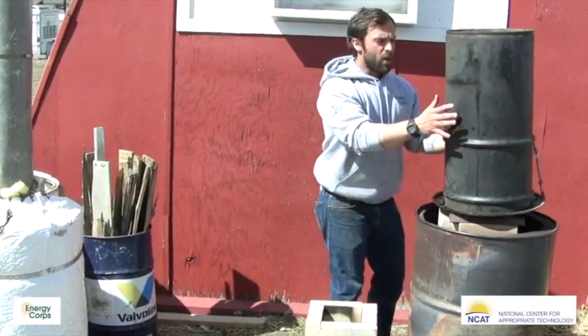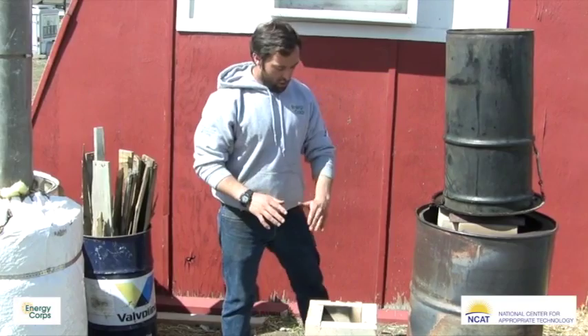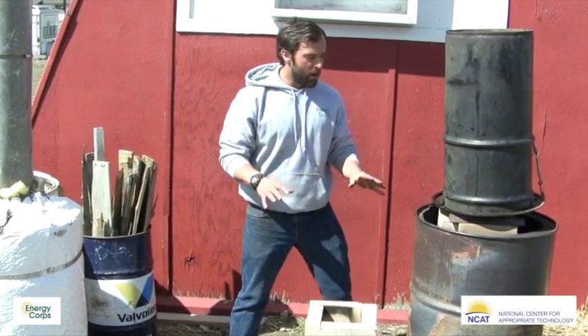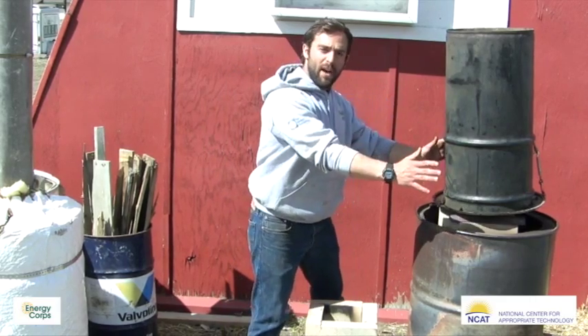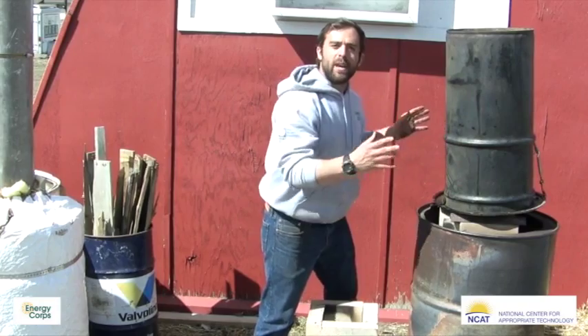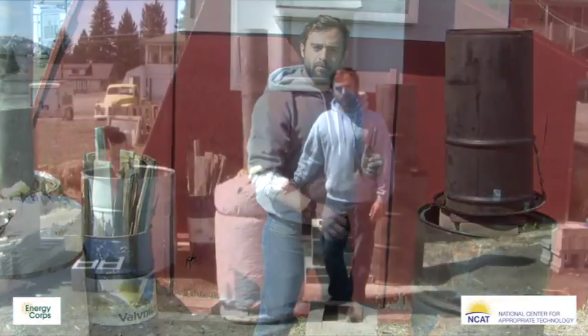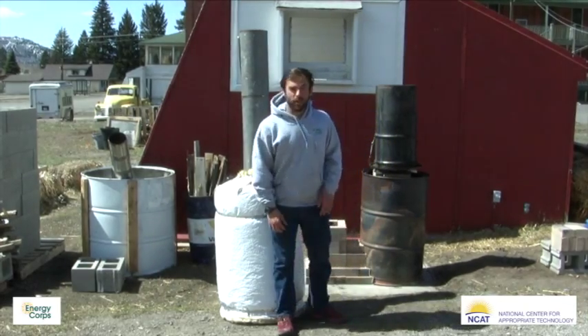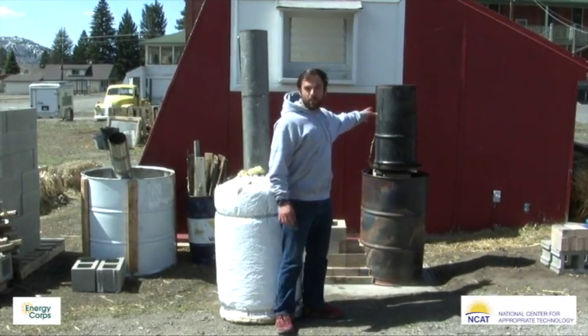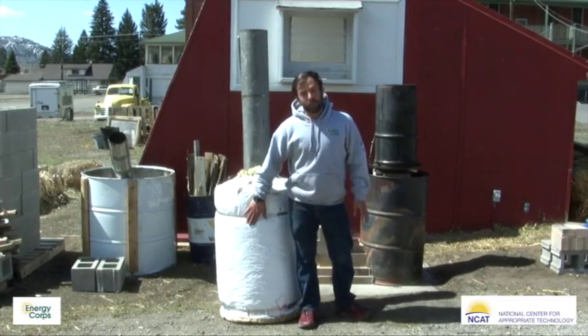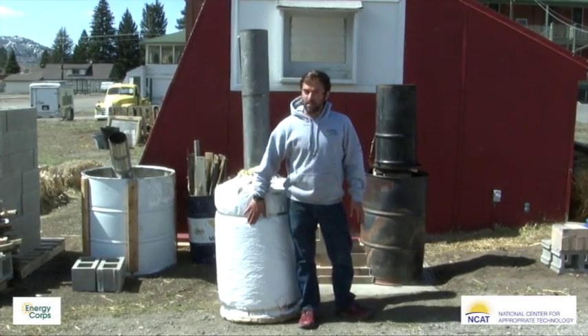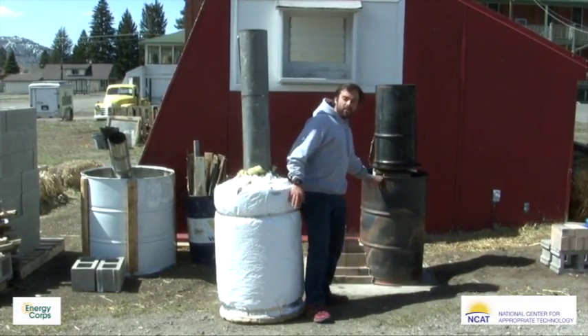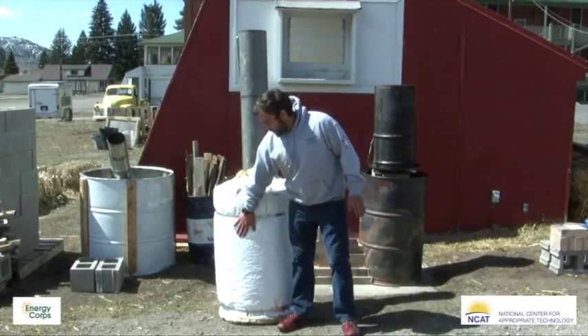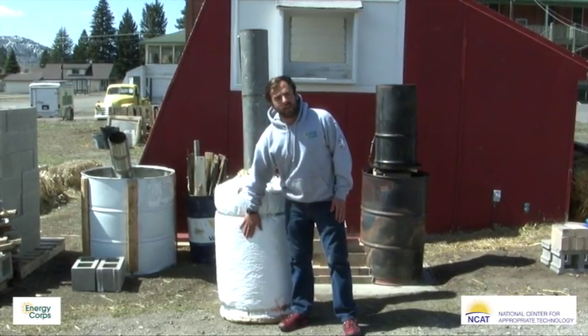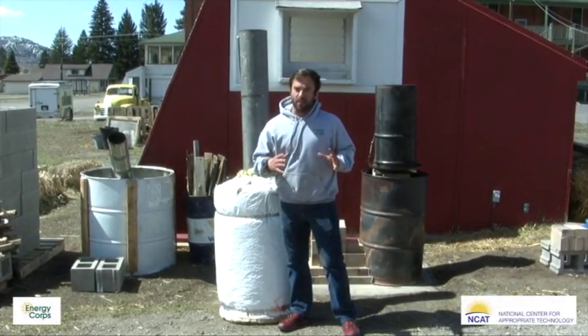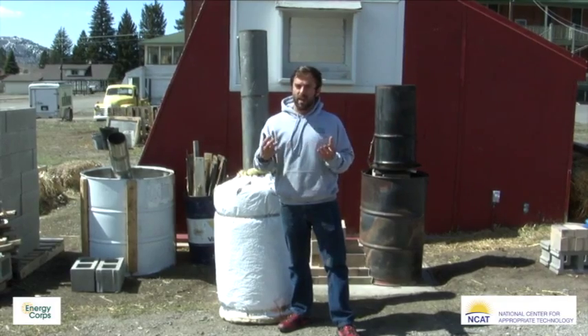So at this point, your biomass is ready to go, your ash pit's cleaned out, and you're ready to burn, but we need to add the second 55-gallon drum around the 30-gallon drum to help contain some of the heat. Okay, so now that we have the retort loaded, the biomass is loaded and the retort is in place, we then add the upper 55-gallon barrel with the fiberglass insulation around it on top of here so it's nice and flush. So this barrel features an insulating blanket around it, and this helps keep heat in instead of radiating to the outside, especially on cold days.